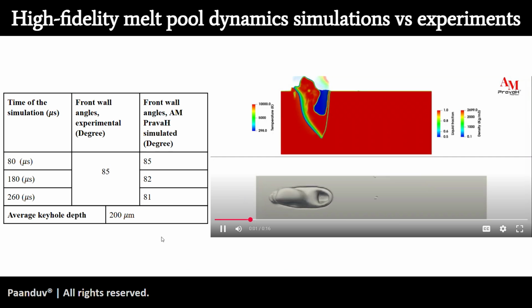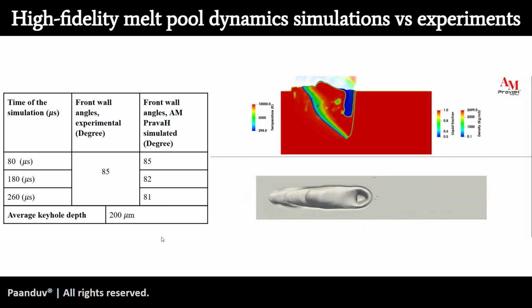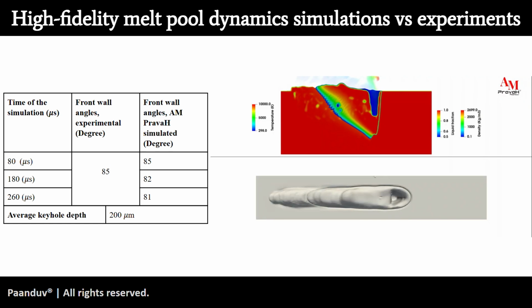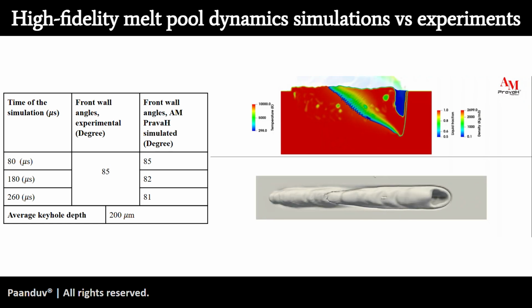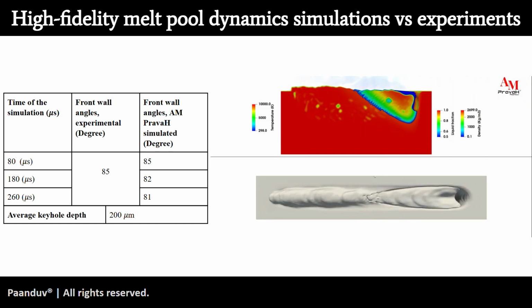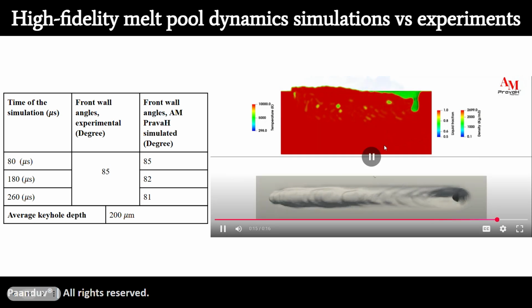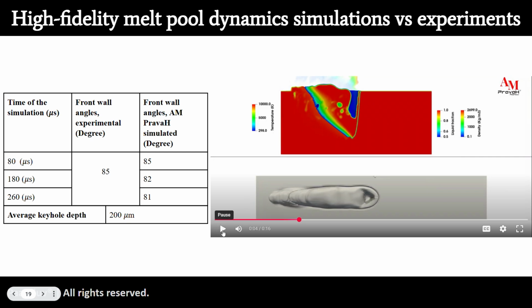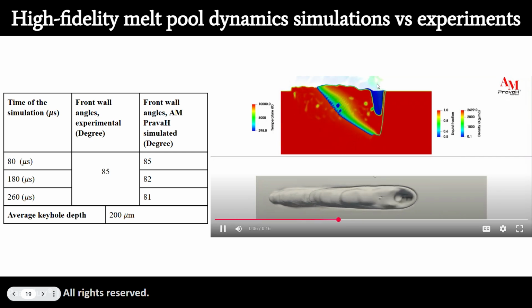I want to play another video from a different angle and at an even higher fidelity. Just look at the pore formation, how some of the pores are stuck in the solidification phase, some of them get ejected out. Even observe the plume, the vapor plume. I will play this one more time. Just observe the vapor plume which is coming out from the melt pool.